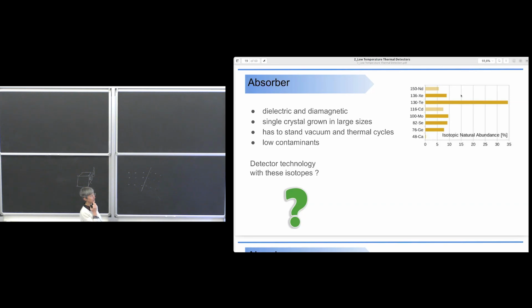I don't. And there is a scintillator that we plan to use for CUPID. There is more than one scintillator that we plan to use, but they are really poor scintillators. So in that case, the energy resolution suffers, and moreover, they have a light production that is sizable only when you are at low temperature. You may know that the amount of light emitted by a scintillator generally increases when you cool it to low temperature, down to the temperature of liquid nitrogen. I mean, you do not need to go to 100 millikelvin or 10 millikelvin.